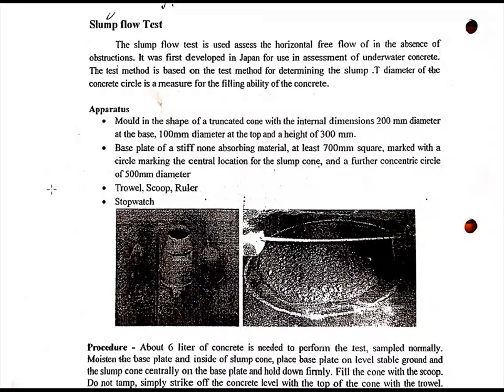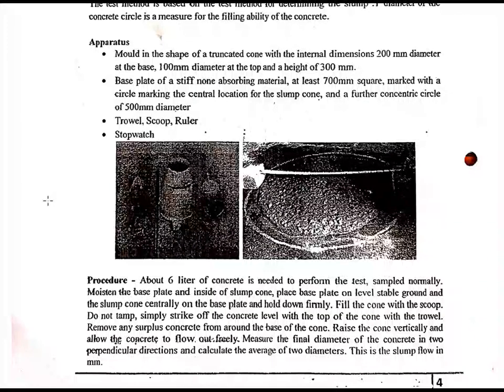Slump flow test. So, slump flow, as you all know, the main apparatus required is a slump cone, a table or a measuring tape, and also a stopwatch. Here we require around 6 liters of concrete. You can observe I am expressing the quantity in liters, not in cubic meters, because the concrete is in flowing form, almost a semi-liquid form. That is why I am measuring the concrete in liters.